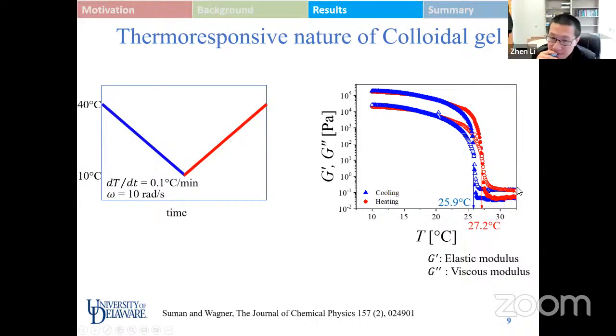Yeah. Right. So firstly, it depends on the initial and the final state of each cycle which we are starting at. In the cooling cycle, we are starting at a higher temperature, which is the liquid state, and it follows a certain curve. While increasing the temperature, the system is ideally not able to undergo the same transition or the same rearrangements which it went through in the cooling cycle. Therefore, there is a little hysteresis in the value of the bulk modulus as seen over here. So basically, the rearrangements which the particles undergo are not identical in both the cycles, which results in a little bit of difference in both the intersection value and the modulus value.